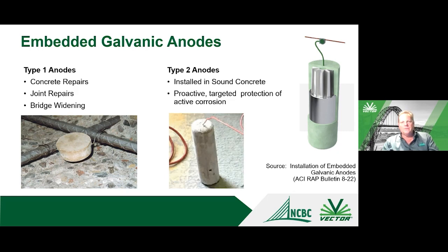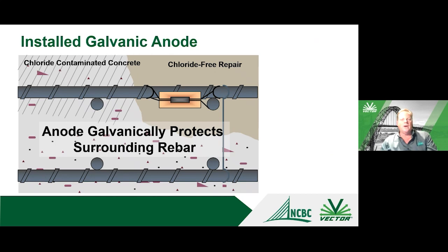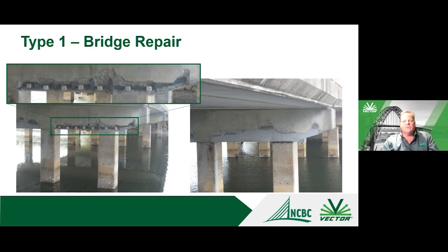But these definitions really come out of the ACI repair application procedure bulletin for embedded anodes. So the idea here is that we want to use an anode in the repair to effectively keep the new anode, or the new area that's corroding, from being shifted to the adjacent concrete. So these galvanic anodes, they're sacrificial. They're made of zinc with an activating mortar to keep it active over time, and the zinc sacrifices itself instead of the steel.